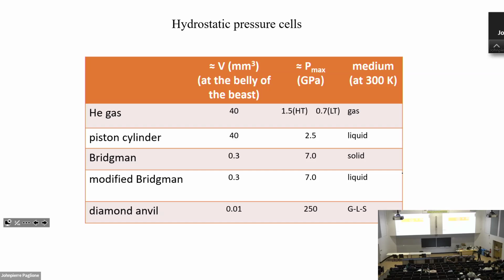And the hydrostaticity is slightly worse. And you can go to 7 GPa. Later on, people modify this type of pressure cell so that you can include the liquid as a pressure medium. And you can go to 7 GPa. And then now we have diamond anvil cell. You can go to above 200 GPa.